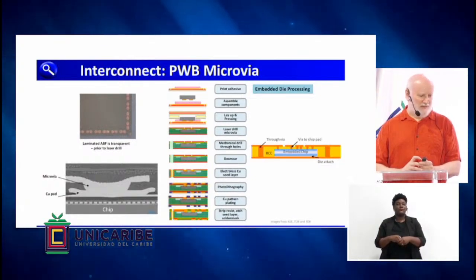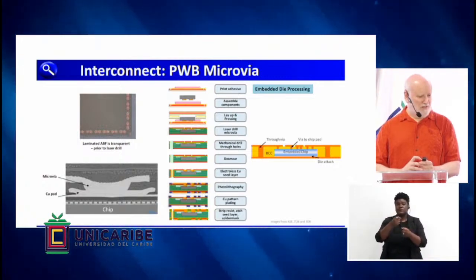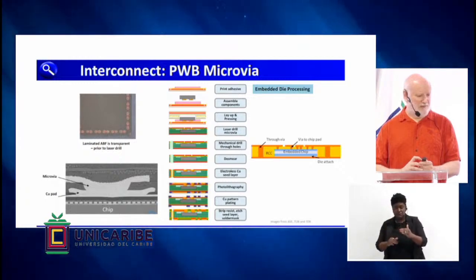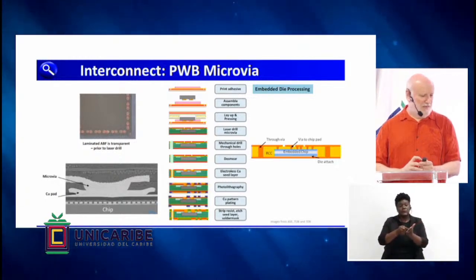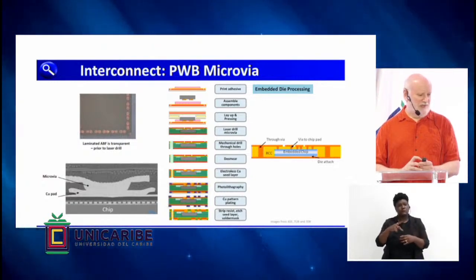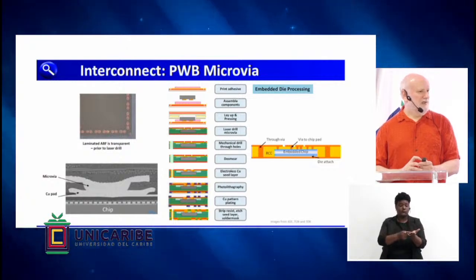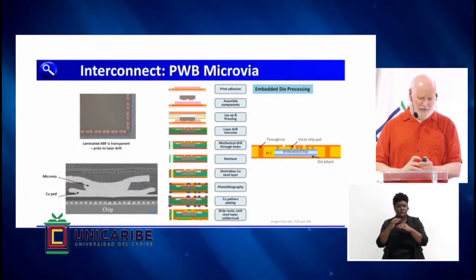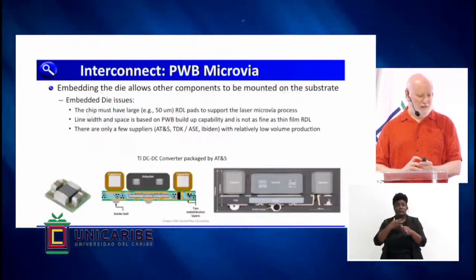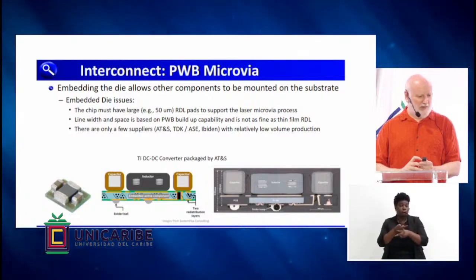This is just going through the process steps I just described, but you can see there on the lower left in the picture what these might look like. There's a micro via that's connected to a pad on the chip. The pad has been coated with a thick copper layer because if you didn't do that, the laser could burn through a normal chip pad, so you have to modify the pad on the chip. So this is an example of a part made that way. In the center of this part is an embedded die with the connections by microvias. What you can see in this case is that it opens up the top of the package substrate where they can mount other components. So in this case, they're mounting inductors and capacitors on the surface.